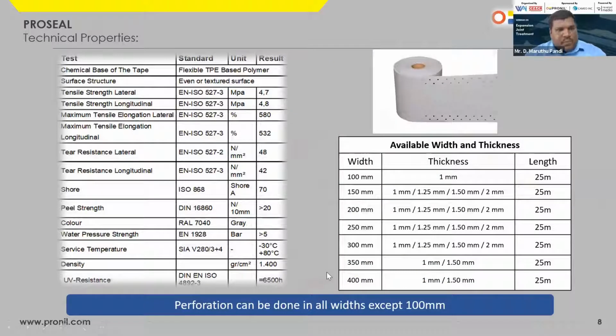And these are the technical properties of our expansion joint tape, TPE, thermoplastic elastomer. The base chemical composition is a TPE based elastomer, and the surface is knurling textured, which will have better bonding with other hybrid coatings also, and can be exposed to sunlight. It has a very good lateral and longitudinal strength of almost 4.7 to 4.8 MPa. Elongation is more than 500%, with very good tear resistance and a shore hardness of almost 70. Peel off strength is greater than 20 Newton per 10 mm. Color is gray and it's customizable also. We can have colors according to the customer's requirement.